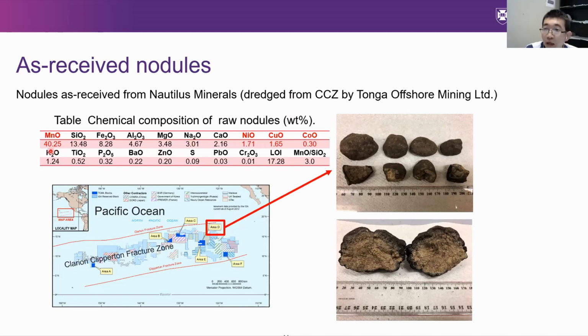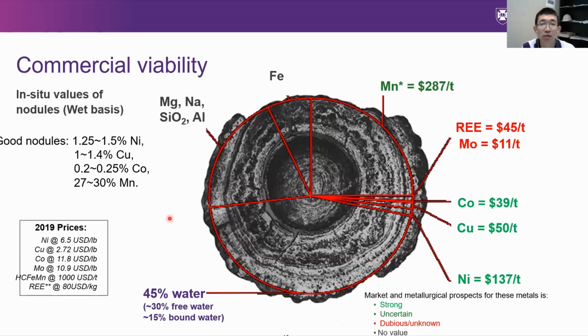For the metals of interest, the nodules contain around 40% manganese oxide, 1.7 nickel oxide, 1.65 copper oxide, and 0.3 cobalt oxide. For molybdenum, vanadium, or rare earth metals, the amount is very low, so I didn't show them here. This is actually a very good nodule. So just based on the price of the metals, we calculate the values of the nodules based on the critical metals and also the major component manganese.